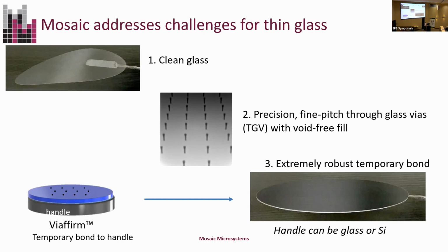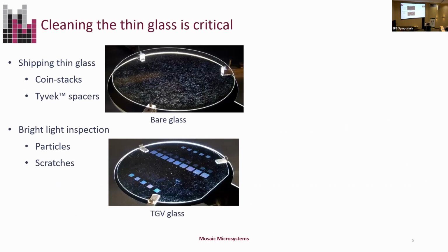And the bond is the trick there. So I mentioned that the glass does not arrive semiconductor clean. This is just a bright light underneath a piece of glass, and you can see that's the light bouncing off particles. It's not nice. In this case below, this is just a test pattern of TGVs, some dense squares of TGVs, again, on incoming glass.